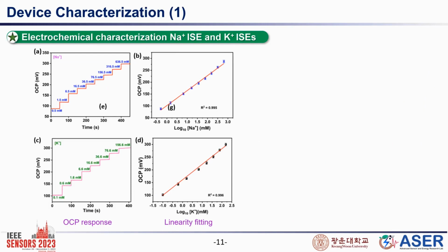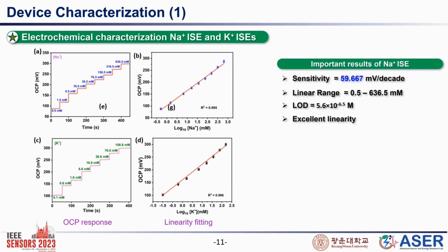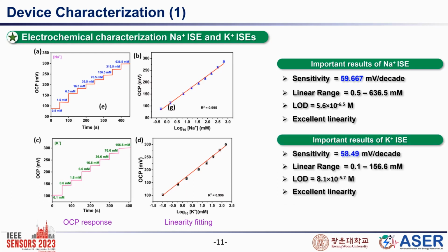Then we go for electrochemical characterizations of our ion selective electrode. So this shows the OCP response and the linear fitting of our two sensors, the sodium and potassium ion sensors. It shows very good response and a very wide linear range for the sodium and potassium ion sensors. And sensitivity we have calculated for the sodium ISE, that is around 59.6, and linear range 0.5 to 636.5 millimolar, and LOD is very low and excellent linearity, we can say. And in addition, we have calculated the sensitivity of the potassium ISE, that shows 58. It is also very close to the ideal response, and the linear range is very comparable if I compare with other published papers, and also the LOD.